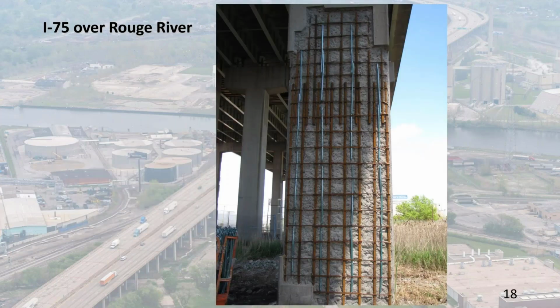So anyhow, as we can see here, the first step in applying this FRP reinforcement was to remove the unsound concrete from the pier columns and expose the steel for a better bond and performance. And in addition to the FRP, we wanted to ensure longevity by placing sacrificial anodes to protect the steel from the ring anode corrosion effect, which essentially combats the issue when you place new concrete next to old. You form an electropotential that accelerates corrosion in the old concrete. So to mitigate that, we threw in the sacrificial anodes.